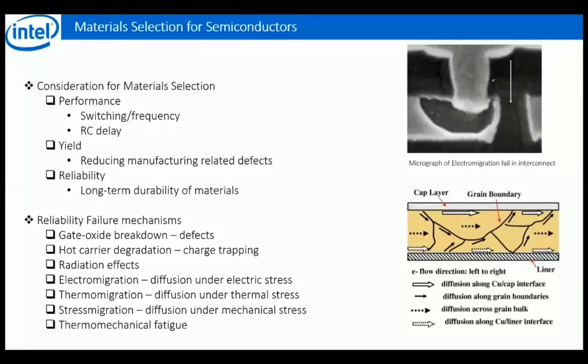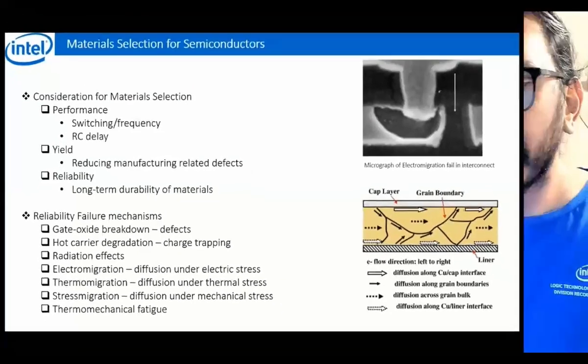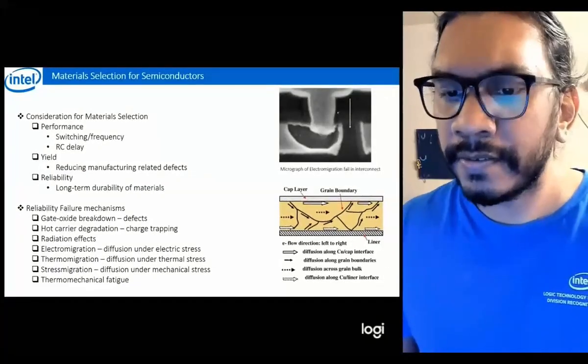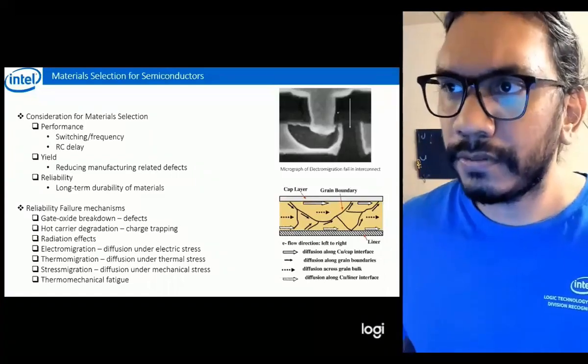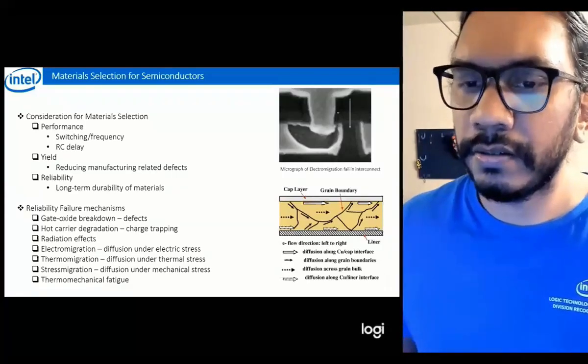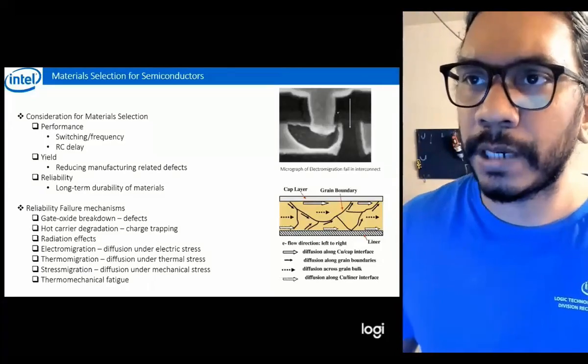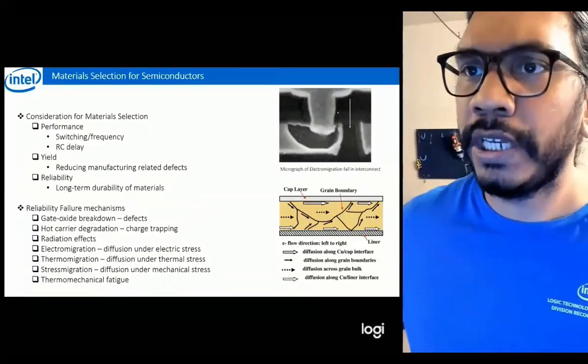And we see that in our C4 bumps where the CPU meets the main board. We have these big tin and lead bumps that go through huge fluctuations of temperature. So there's expansion and contraction, and with that expansion and contraction, there are tensile and compressive stresses. So I've gone through all the failure mechanisms. These things don't happen in the moment you turn on the CPU. It happens over weeks and months.